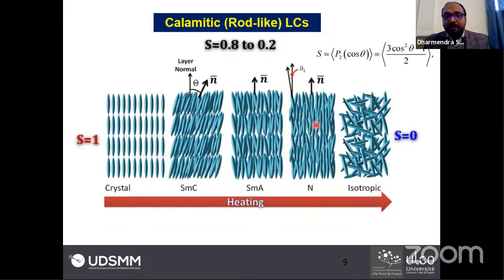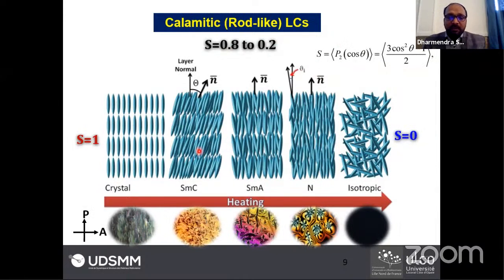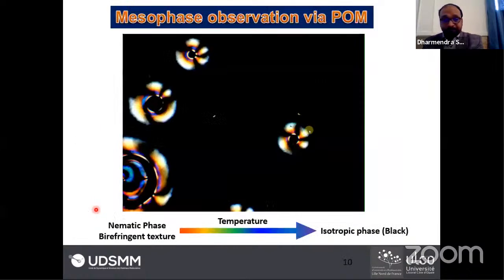And you can obtain the order parameter in different phases. For the crystalline phase, the order parameter will be 1. For the isotropic liquids, because there is no order at all, the order parameter will be 0. And the order parameter for liquid crystalline material lies between 0.2 to 0.8. You can calculate the order parameter using this formula. And different mesophases can be observed by polarized optical microscopy under crossed polarizer and analyzer condition.